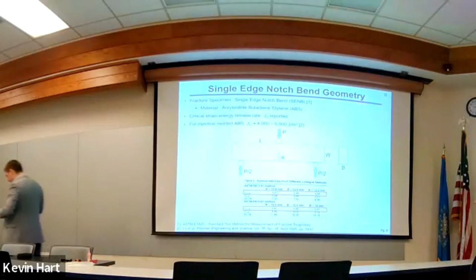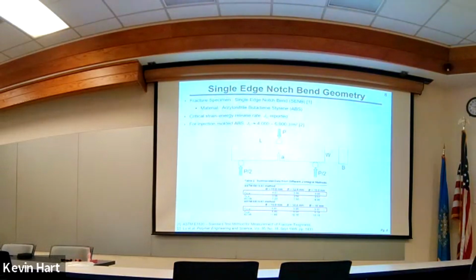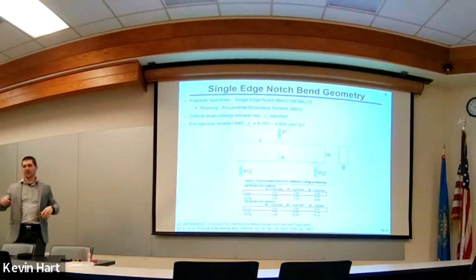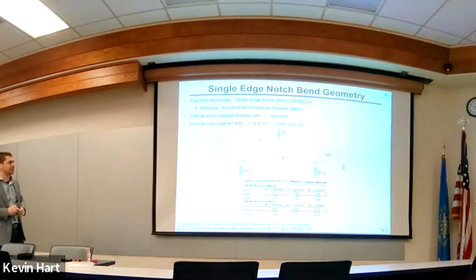So keep that number in mind because I'm going to talk about 3D printed samples in retrospect. Here's a single edge notch bend specimen that we tested. You can take a look at the crack underneath, and you can see the whitening in front of the crack tip. That's some of the plasticity, for those of you that are interested in that sort of stuff. The crazing, the whitening in front of the crack tip, gives you the toughness that you like.